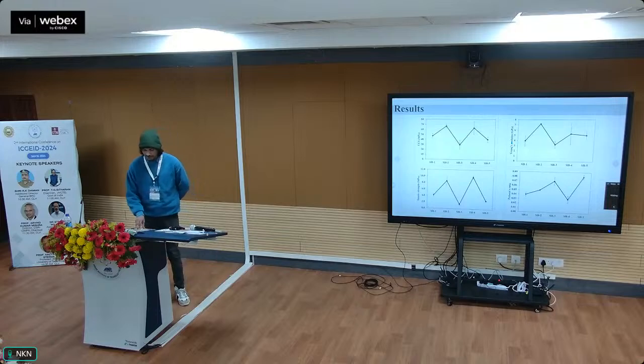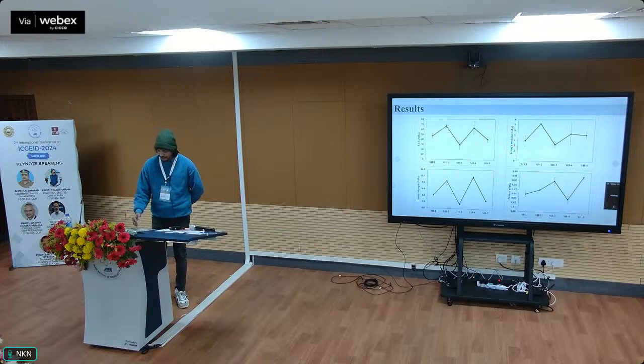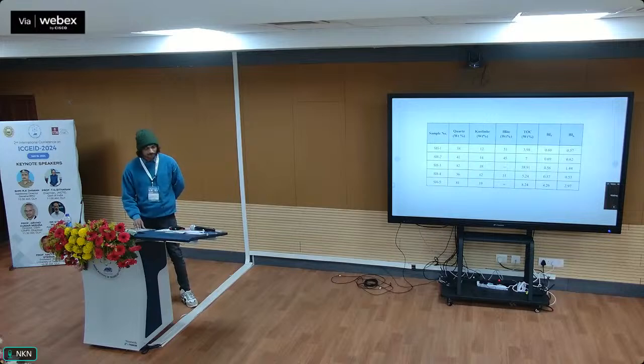These are the results. We found that coaly shales showed very less UCS compared to other samples, and the highest was shown by intercalated shale. These are the XRD and TOC calculation of the samples. So the TOC varied from 3.98 to 38.91, which is very high. And I must tell you that we had also calculated the hydrocarbon potential of Rajmahal Basin. So those samples were mainly type 2 to 3 kerogen. So those had potential of gas generation. So that's why we have taken samples from there.